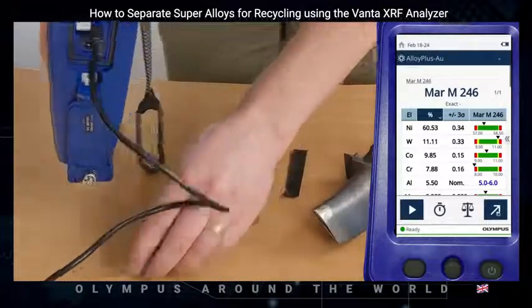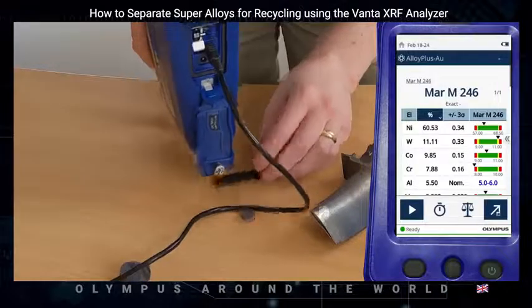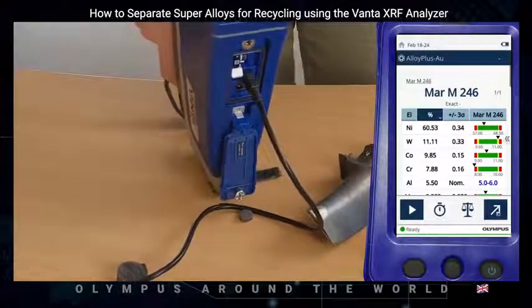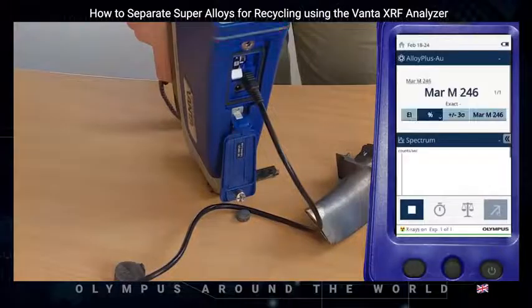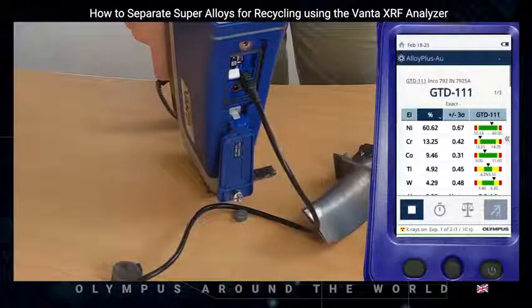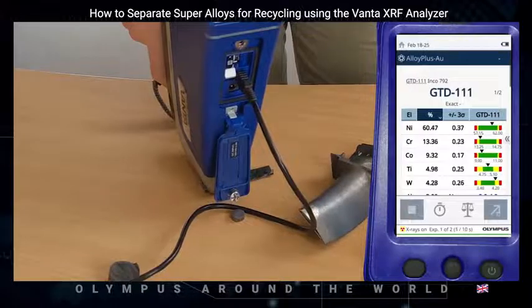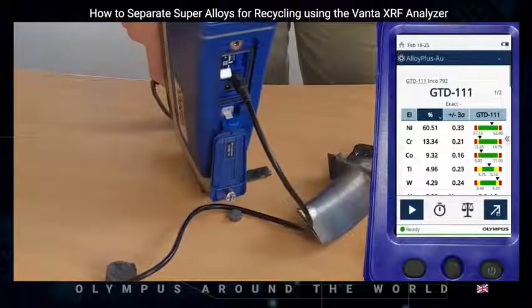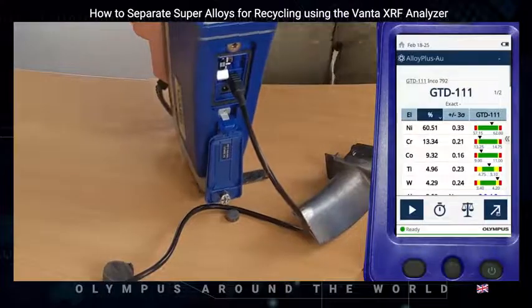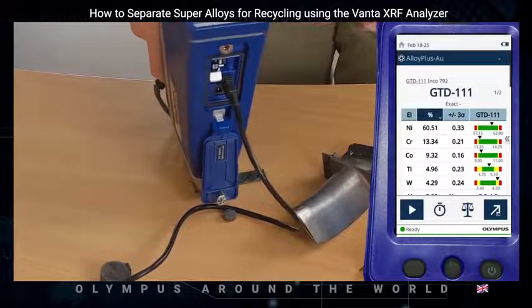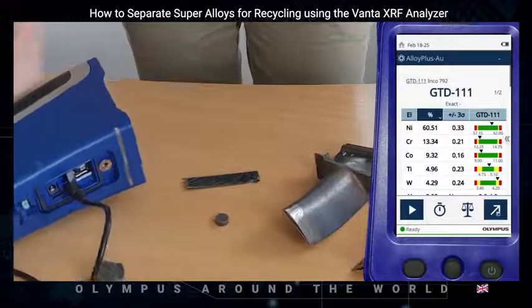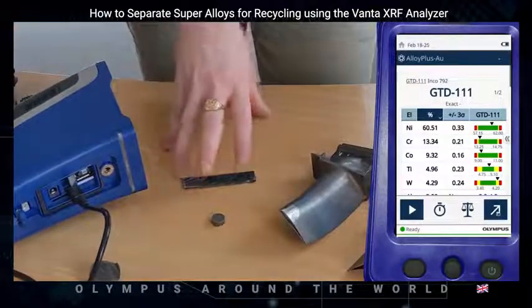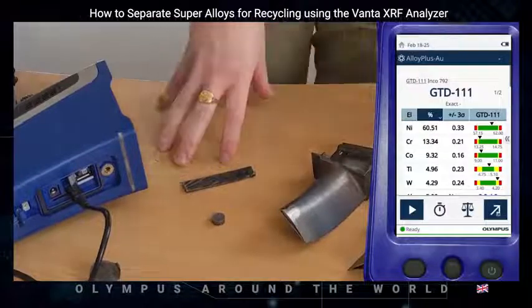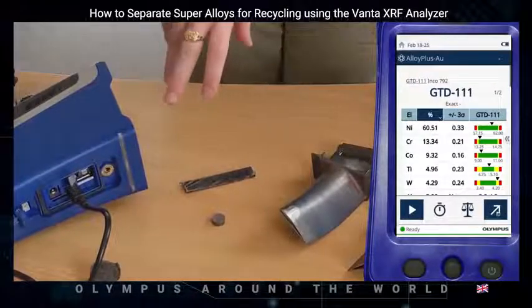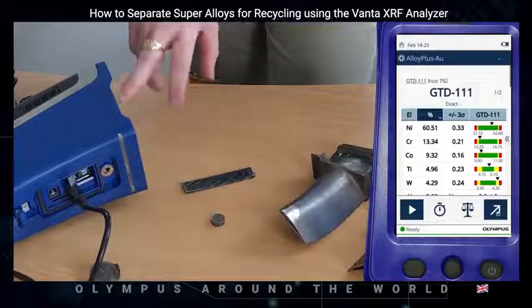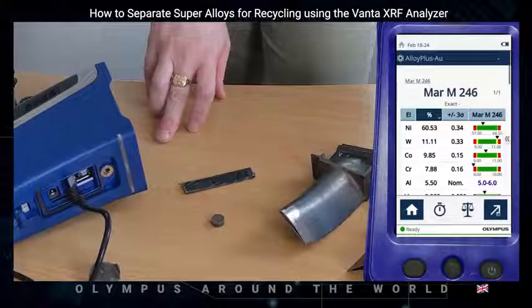So that material's MAR-M246. And you can see very quickly, within 2 or 3 seconds, we get a good grade match, GTD 111 for this sample, and the chemistry is displayed below. Note these samples are not particularly clean, they're not flat, and this can sometimes change the result. However, we did get grade matches for those two samples of GTD 111 and MAR-M246.